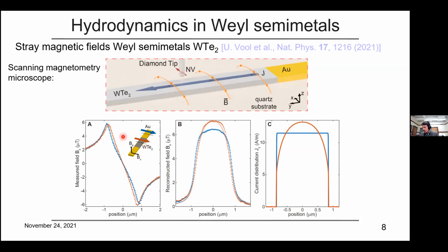As you can see from this figure, for example, the measured normal component of the magnetic field agrees very well with experimental data. These solid lines agree well with experimental dots. Furthermore, one notices that qualitatively, the shapes are quite similar, both for gold and for Weyl semimetal. In the case of the longitudinal component of the magnetic field, there is a larger difference between gold and Weyl semimetal, and also we notice a large agreement between the experimental and theoretical data.